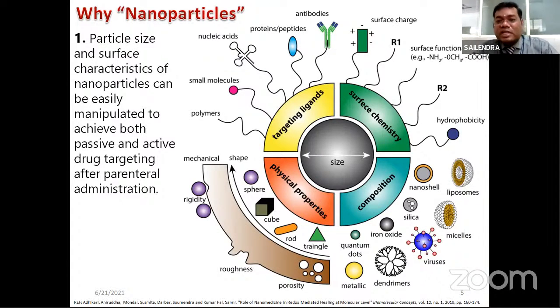But if you see the positive side, we can utilize this function for surface functionality. You can attach different functional groups depending on the charge, adsorption on the surface of the nanoparticle, that too based on charge. You can modify the surface chemistry. You can change the hydrophobicity. You can increase the hydrophilicity. So by just modulating the surface chemistry with the help of various chemical substances, we can attach a lot of drug molecules. We can specifically attach different chemical substances that will increase its half-life in the bloodstream, and we can formulate these kinds of nanoparticles.